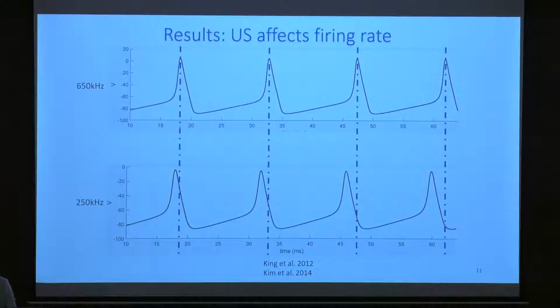And we also noticed a change in the neuron firing rate. So the upper graph shows the action potential when it's stimulating using a continuous ultrasound signal of 650 kilohertz, and the lower one shows 250 kilohertz. And we can notice a difference in the timing where the maximum or the spiking occurs. And this was also shown in some published experimental data.